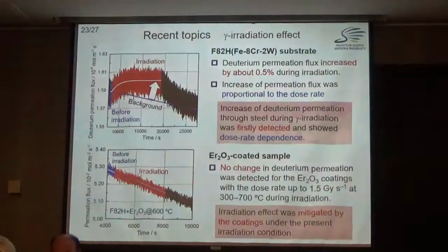With this system, we tested just a steel substrate. In the case of steel, during the irradiation, the permeation increased. I don't know why, but we are struggling to solve this problem. But it is just 0.5% or something like that, up to 1%. The increase of the permeation factor was proportional to the dose rate, so dose rate is important. So the increase of deuterium permeation through steel during gamma ray irradiation was firstly detected and showed dose rate dependence.